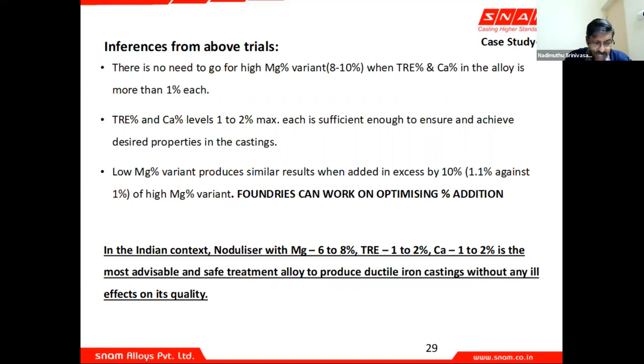We have some foundries in South India, the high pressure line, and we have seen them using the lanthanum-based magnesium alloy at 0.8%. And there are some foundries in the north side also and west where we are seeing less than 1% addition. So today, that fine-tuning is based on your conditions, your treatment procedures, the process, your tapping temperature, the purity of your charge mix. So based on this, you can work on it.